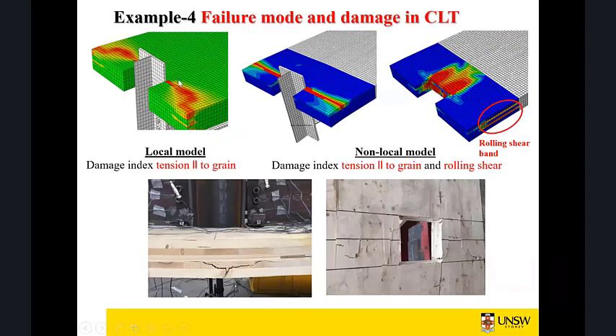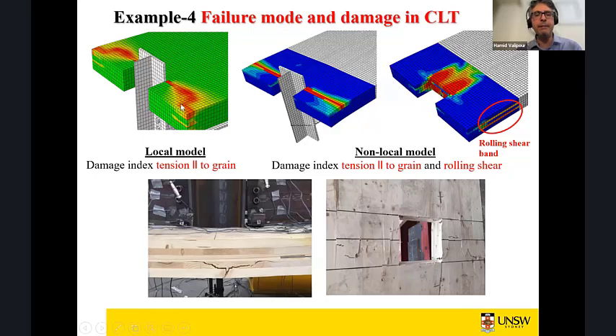Again, I just want to highlight the importance of the mesh sensitivity. You need to keep an eye on this. You see on the left, we have used an ordinary model available in Abaqus. In fact, you see the extent of the damage. And then when we implemented that localization limiter or non-local model, you see the extent of the damage and the damage propagation, as well as the extent of the damage which appears as rolling shear on the lamella loaded perpendicular to grain. This one on the right was quite consistent, as you can see down the bottom with the test.